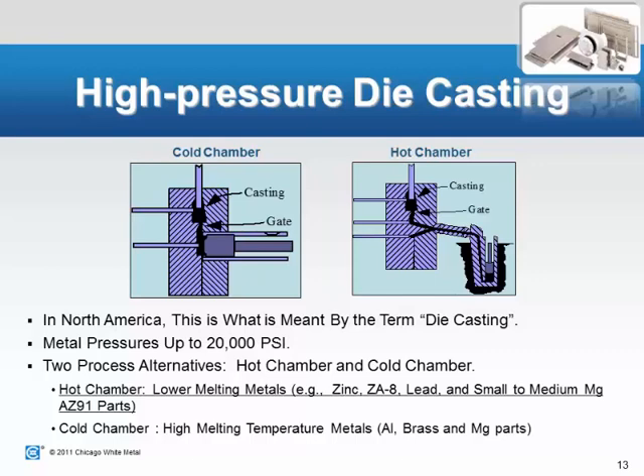The hot chamber process is used for the lower melt temperature metals, so zinc, ZA8, lead, which we don't cast, but is there, and small to medium magnesium parts. Those are hot chamber applications. Cold chamber are for the higher melt temp metals, such as aluminum, brass, and the larger magnesium parts.